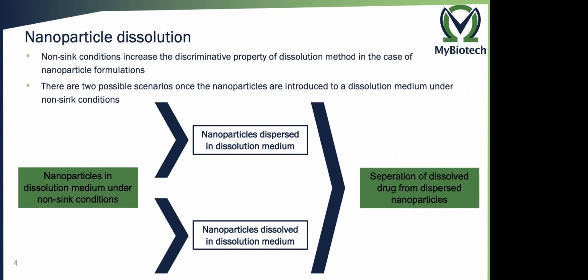Normally, in a conventional dissolution, you do the dissolution under sink conditions, which means solubilities or at volumes higher than the solubility of the API. But in case of nanoparticles, in this advantageous condition, if you put nanoparticles under sink conditions, due to the fact that they all dissolve very fast, you don't see any differences between different formulations. So we also use non-sink conditions for the characterization of nanoparticles in order to be able to understand what the issue is coming from this non-sink condition.